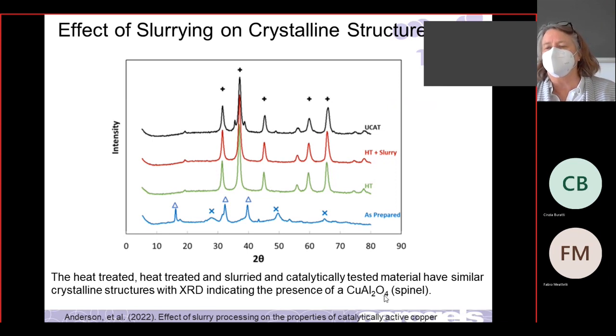It's a chemical structure that was in the heat treated material. This is meant to show it's in the heat treated material, it's in the slurried material, and it's in the material after we test it. So no big changes, except we always see this little bump after we test it, which we think has to do with the environment in which we test this. We see it for almost all of the copper materials. But anyways, there's no difference between the heat treated and the slurried.